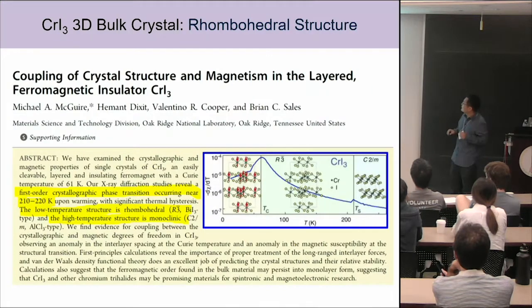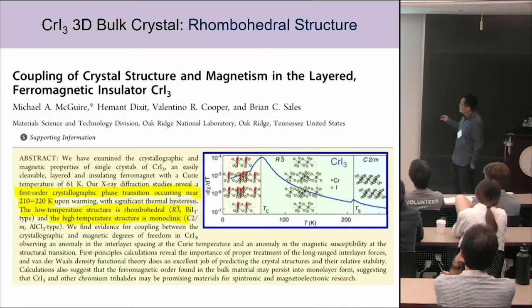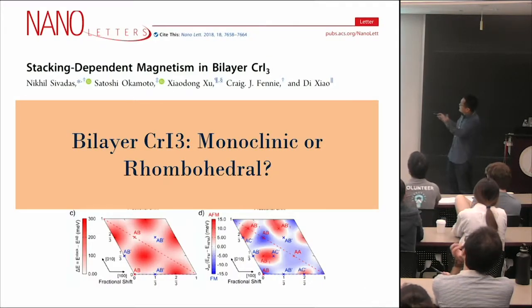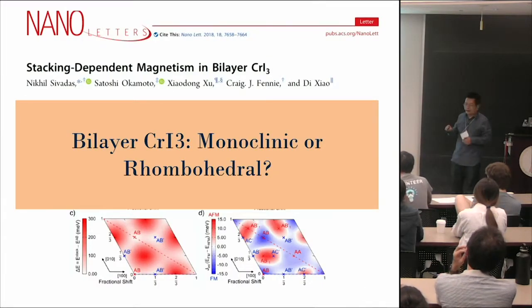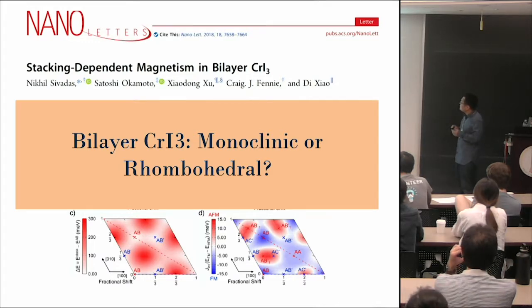Now the question is, what is the stacking order? For the bulk crystal, my collaborator already measured there's a crystal structure phase transition at around 200 kelvins. The high temperature is a monoclinic phase. When you go to low temperature, it's a rhombohedral phase. Therefore, in a bulk crystal, it's ferromagnetic order, consistent with the theory. If it's rhombohedral, it should be ferromagnetic. Now, what's going to happen in these bilayers? Is it monoclinic or rhombohedral?